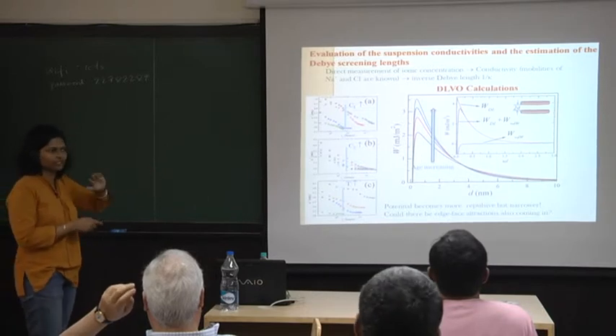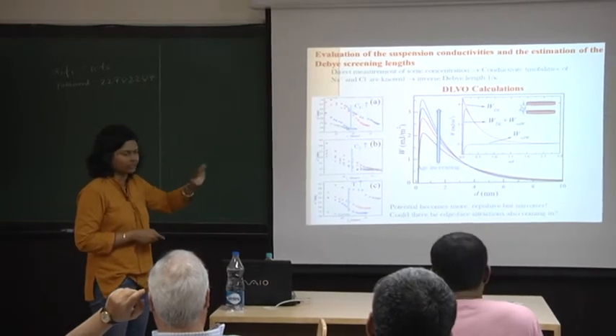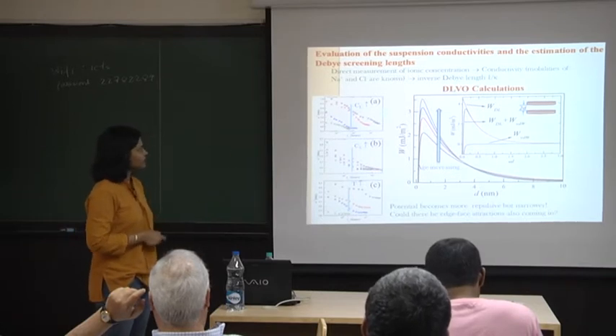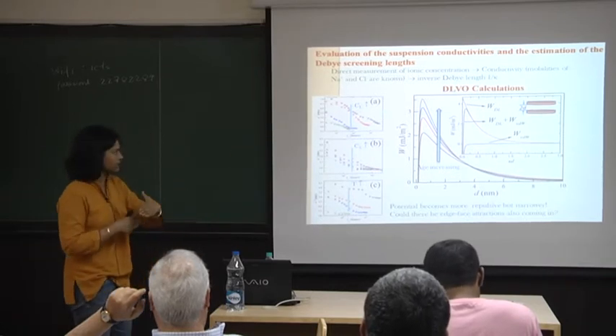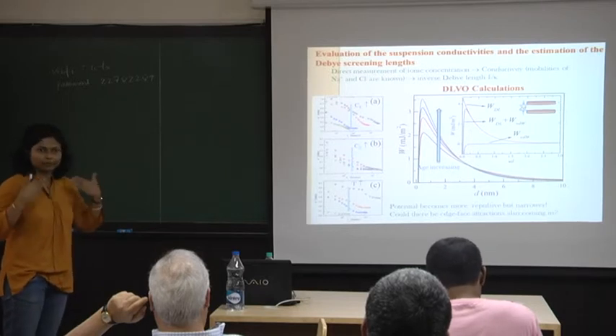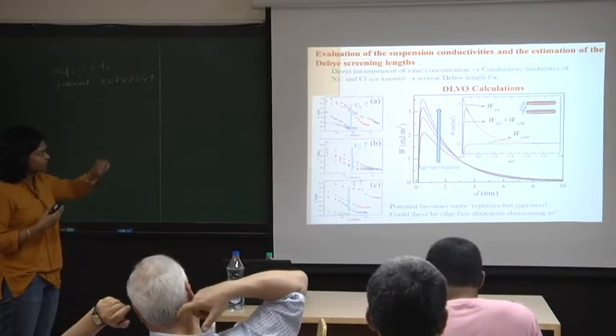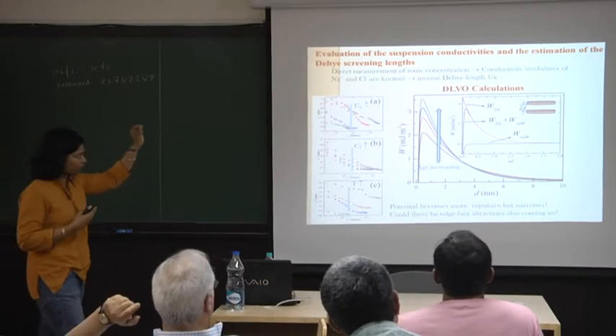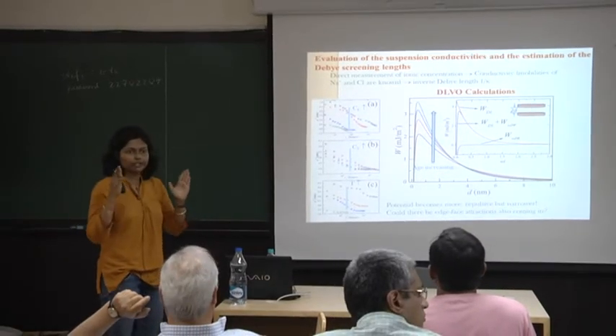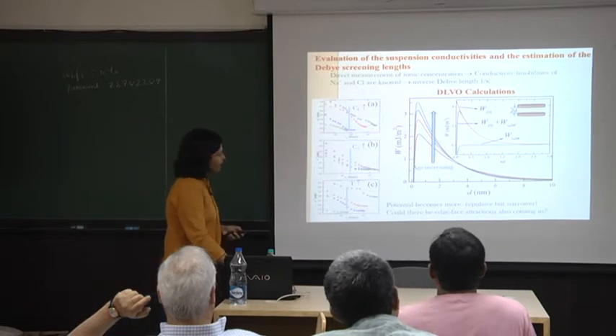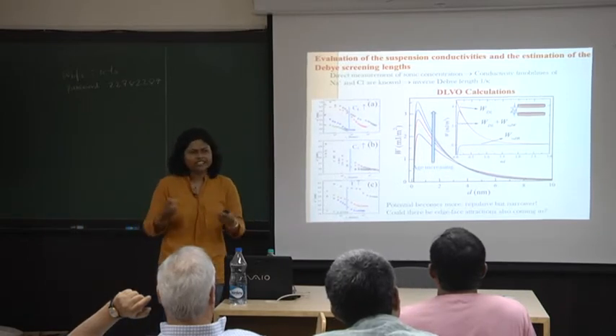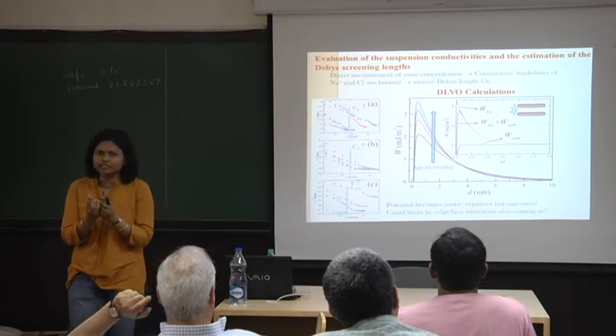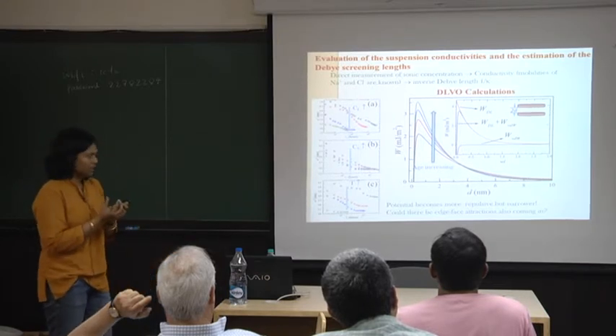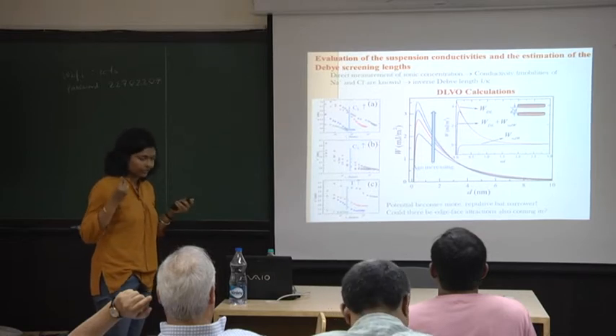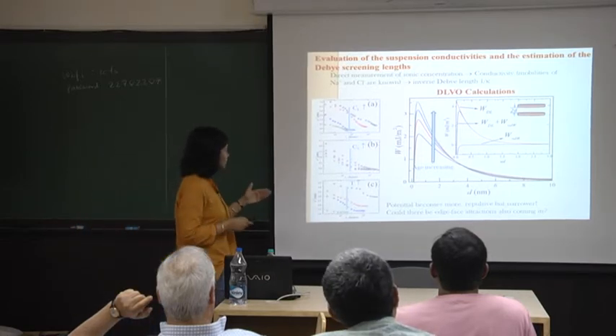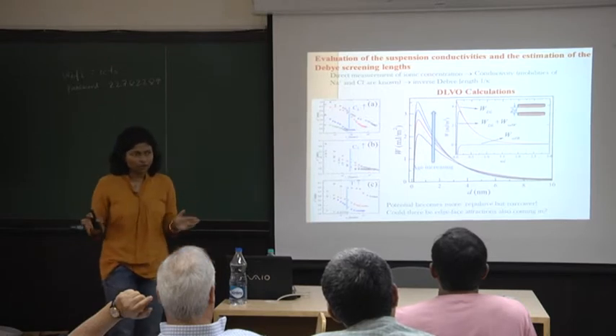The age could be increasing, the concentration could be increasing, salt could be increasing, temperature could be increasing. We see that the interplatelet potential goes the same way: as these parameters increase, the repulsive peak becomes sharper, stronger, goes higher, but the width of the potential decreases. This seems to indicate that within these very short time ranges over which we can take our data, there might be some influence of attractive interactions. I should remind you that this data is taken only over a few hours.